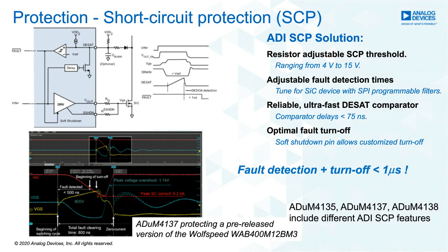So for an IGBT based system, typically we expected short circuit withstand times to be in the 10 microsecond range. For silicon carbide, now we're talking about 3 microseconds and even less. And for GaN, it's even quicker. And then you also have the additional problem that the detection mechanisms that were used successfully for IGBTs are not as effective with silicon carbide or with GaN. We don't have the same detection mechanisms available, so the typical desaturation region is not there for silicon carbide. It's not the same as an IGBT.